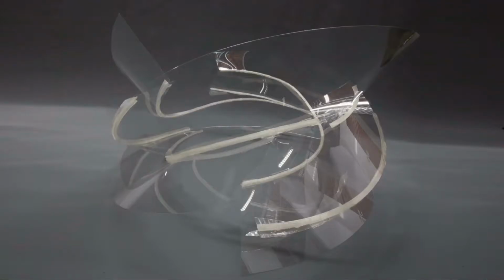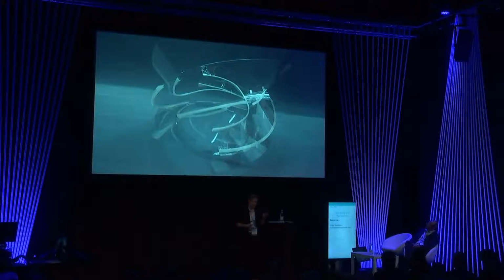And the last one is, you can see here, the glass broke along the edges of those sweeping V's. And what happened there is, I used 3D printers that were limited in size, so my entire sweeping pieces were actually composed of 3 sub-assembly parts. And at the location where I brought those together, I had a discontinuity of stiffness, and that basically created a hinge around which the glass broke. So having continuity of stiffness is going to be important.